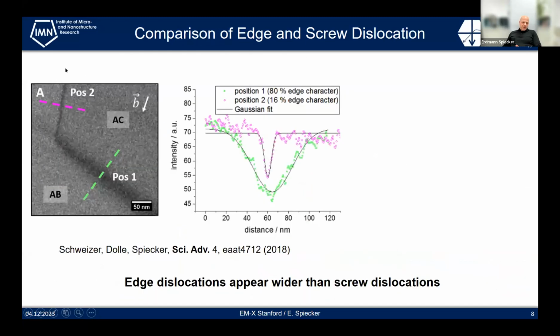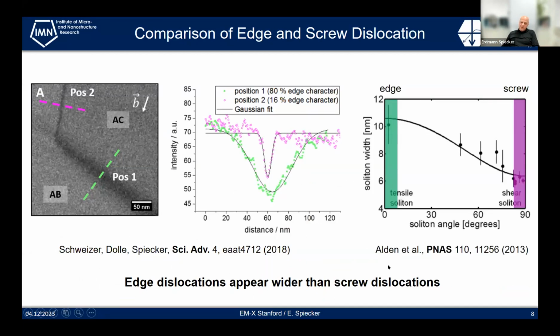There's also a difference if you change direction with such a dislocation, and here's an image where it was more or less a screw dislocation. Here's a Burgers vector, and then it becomes an edge dislocation. The width of the dislocation contrast increases dramatically because of this relaxation. So the strain is dispersed, and so the contrast in dark field imaging also expands. And similarly, this has also been observed by Alden and co-workers, but here it was supported on other graphene layers, so it was not the buckling. Already from the elastic properties, you expect that the edge dislocation is a little bit wider than the screw dislocation.